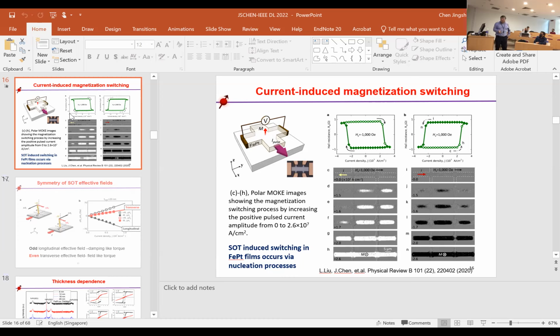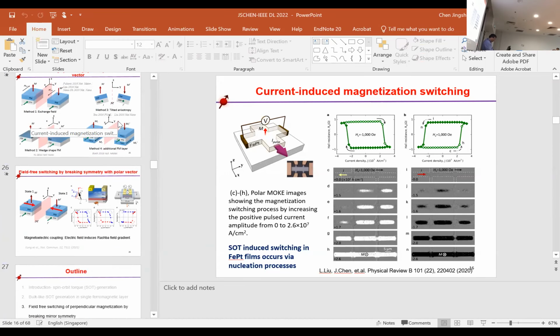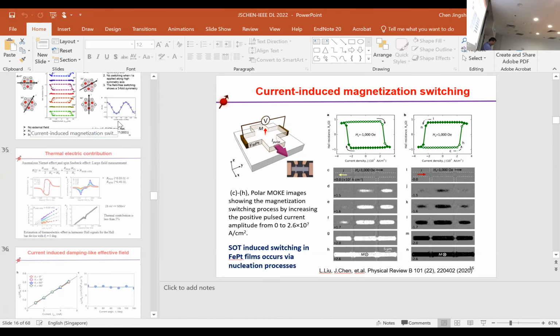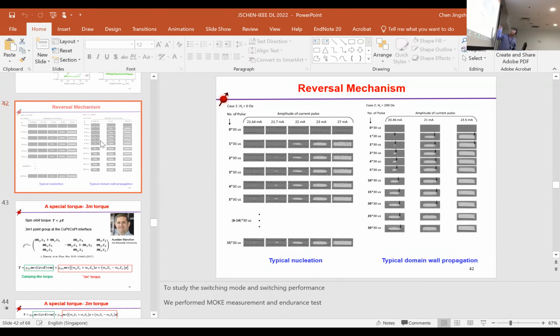Actually, we have demonstrated, when you apply the magnetic field, they will show the domain wall as downward. From here, you can see, right? When you apply the in-plane magnetic field, they show the downward nucleation and expansion. But if you only use the out-of-plane polarization, you can say it is only nucleation. It's not a downward expansion. Because when you apply the in-plane magnetic field, this downward spin texture has changed, due to the chirality effect.